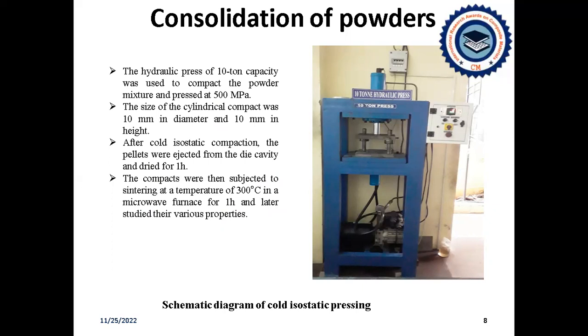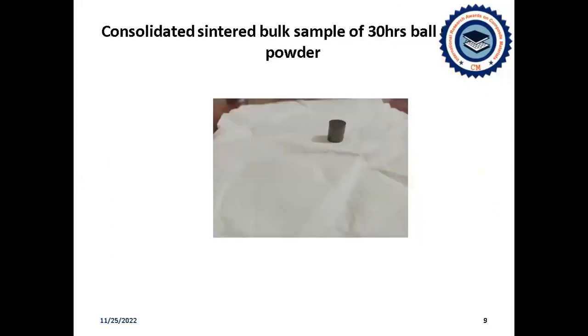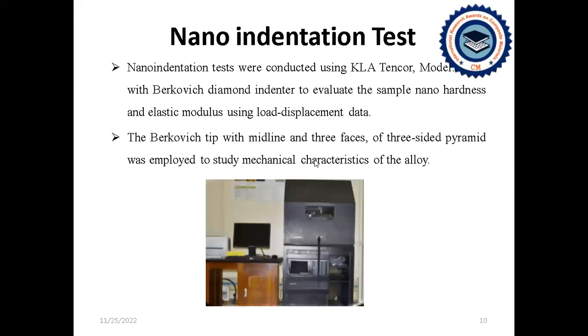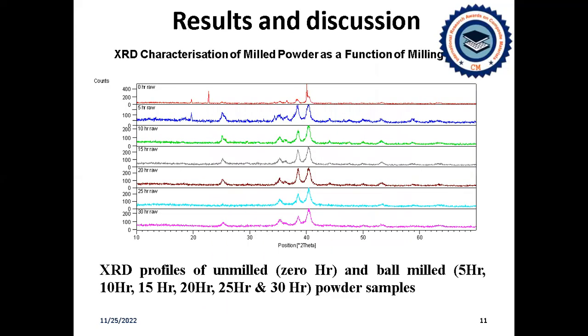And later, the compact sample was characterized to know its structure and properties. This picture shows the bulk compact sample which was synthesized from the 30 hours ball milled powder. Nano indentation test was carried out in order to study the mechanical properties of the compact sample, particularly the hardness as well as the Young's modulus. In order to know the Young's modulus of the sample, nano indentation test was carried out.